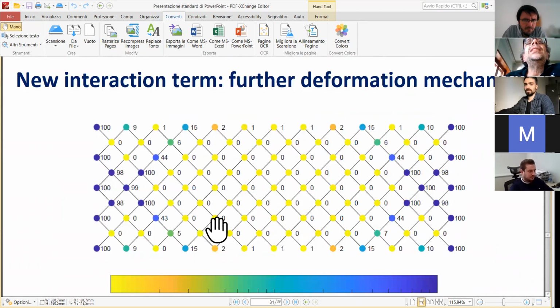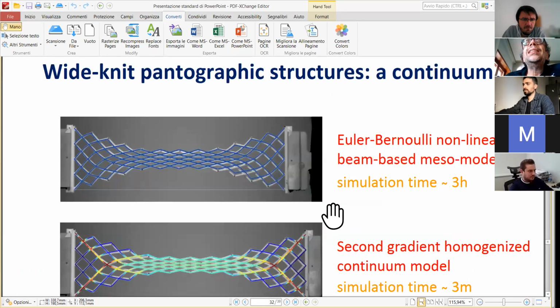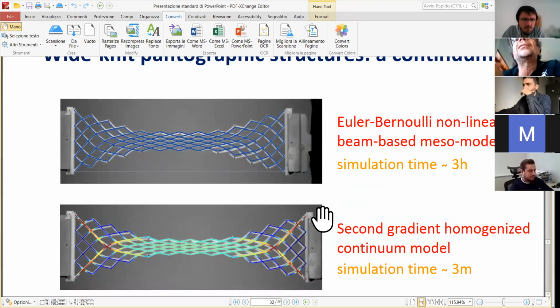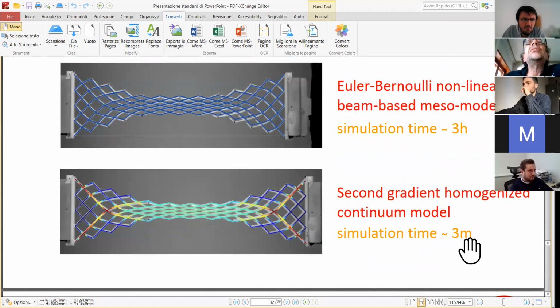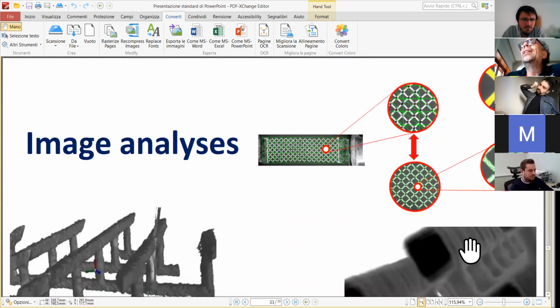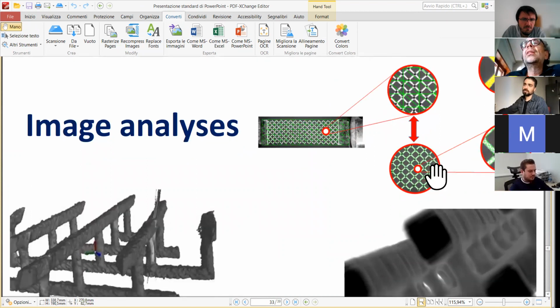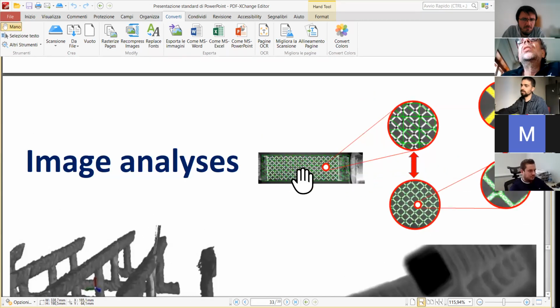Now, if you want to find this optimized scheme, you need to solve the elasticity equilibrium problem several millions times. So if you have that each simulation lasts 3 hours, you are lost. You cannot find the optimized structure. If you have 3 minutes, this is feasible, and we did this. Okay, now I want to give some hints about what we have done with image analysis for checking the quality of our theoretical models. Now, also in image analysis, you can have different layers, different length scales in analysis.